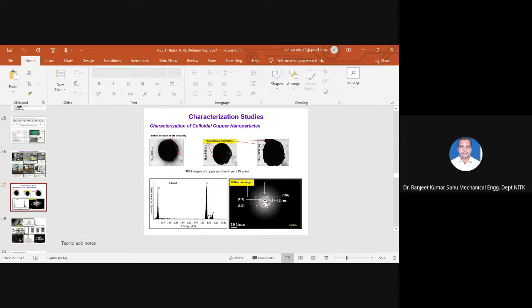The diameter from the center to each ring is measured here. The first ring diameter yields a lattice spacing, that is d. d is nothing but the lattice spacing or d-spacing of 0.21 nanometer for the 111 plane. So this 0.21 nanometer perfectly matches with the FCC crystalline lattice distance of copper in powder diffraction. We observed that one. Similarly, the lattice spacing for the next 2 rings for the 200 plane and 220 plane also perfectly match with the FCC crystalline lattice distance of copper. So finally, it is observed that the copper particles which are produced in the dielectric fluid are of pure metallic copper.